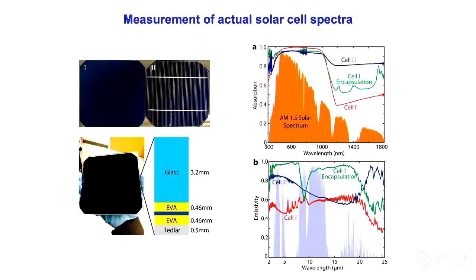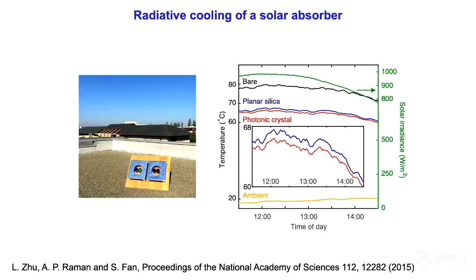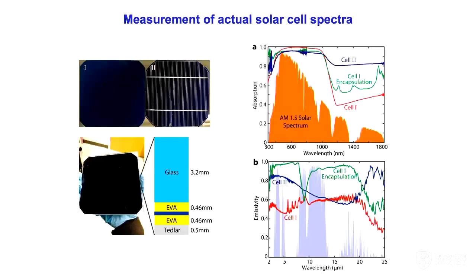One would like to translate this experiment that we have done into a solar cell demonstration. This is actually a solar absorber demonstration. So with that, it would be useful to measure the solar cell spectrum. A typical solar cell already has a glass encapsulation layer. Now, if you look at a silicon solar cell, what you see is that it absorbs the visible part of the wavelengths up to 1 micron, where you can use it. But it also still absorbs a significant amount of infrared light that doesn't produce photocurrent, but serves only to heat up